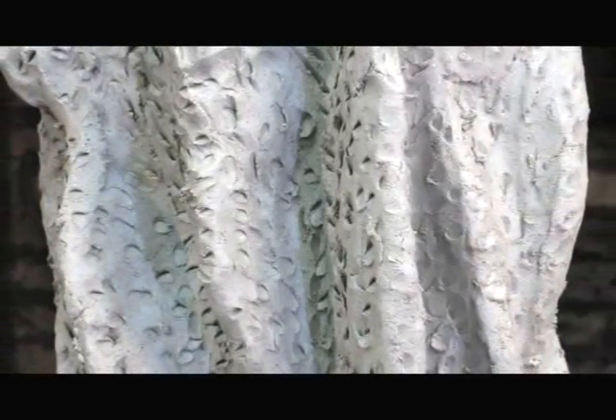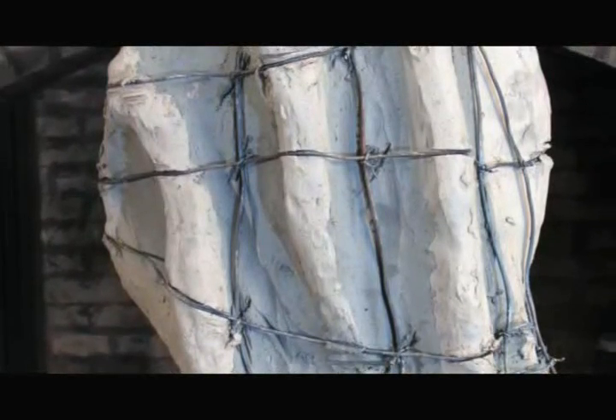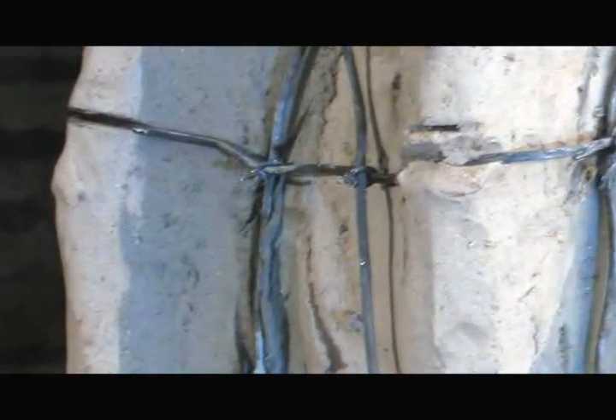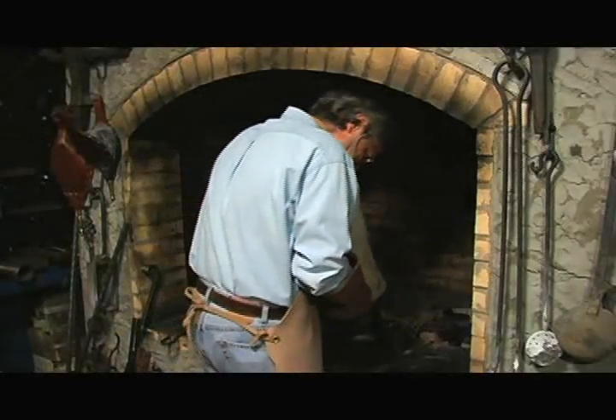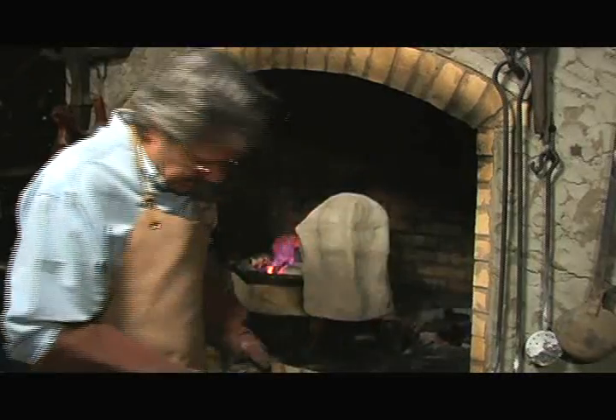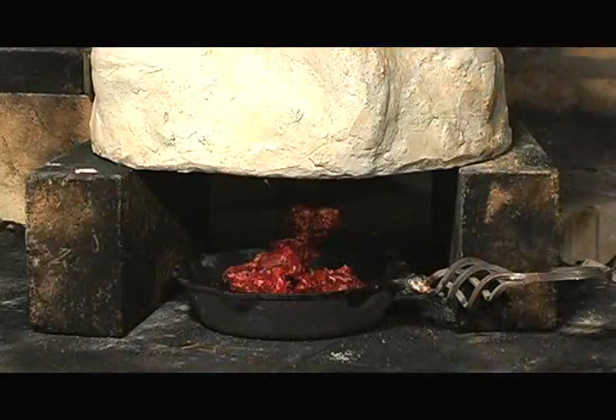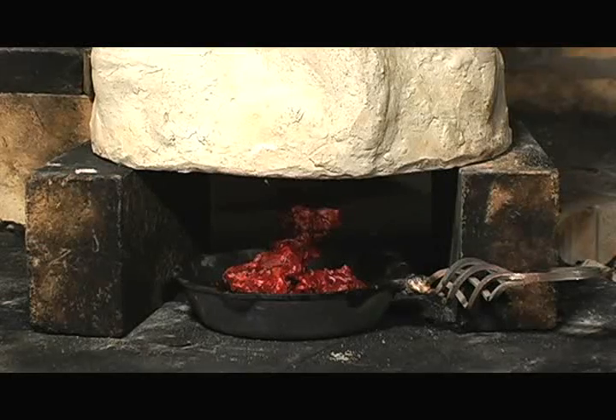Layers of coarser refractory clay were applied over these initial coatings, with each layer allowed to partially dry. We have assumed that a cage-like wire structure was embedded in the clay as a reinforcement before the final layer was applied. Once the mold was completely dry, it was placed near the fire in order to allow the heat to melt the wax, a precious commodity whose recovery was essential. The core and the investment would then be cured and the wax completely burned out by firing it in a furnace of sufficient diameter to allow charcoal to be placed between the interior walls of the furnace and the walls of the investment.